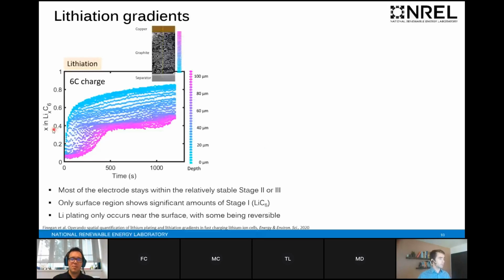And on the y-axis here is the state of lithiation, x in LixC6, and the x-axis is time. And the points are color-coded as a function of depth. So 0, again, is close to the separator, in blue here, and as it approaches the current collector, it goes to purple. So you can see that the areas close to the separator pull away very quickly in state of lithiation, while regions close to the current collector don't respond at all for the first couple of minutes, or first minute or so. And so this shows the extent of lithiation gradient.